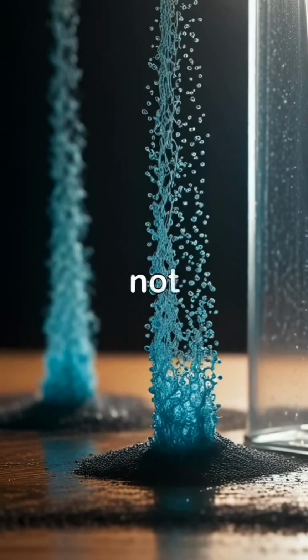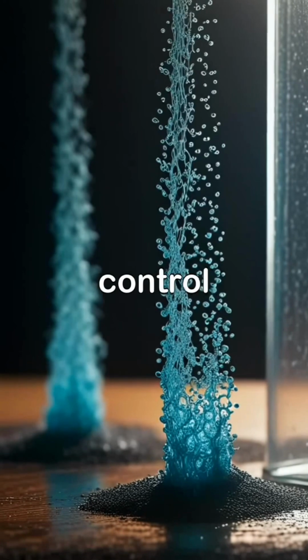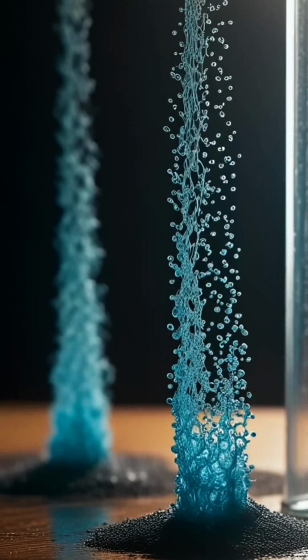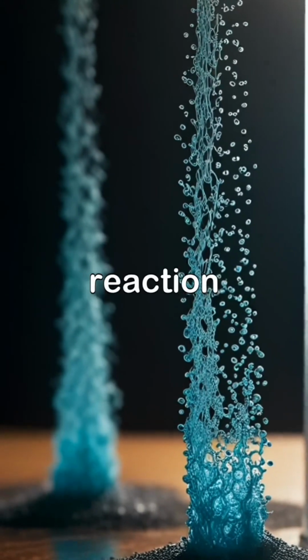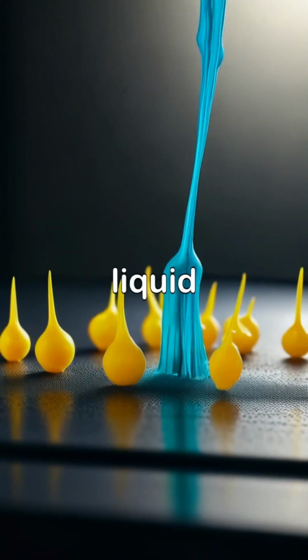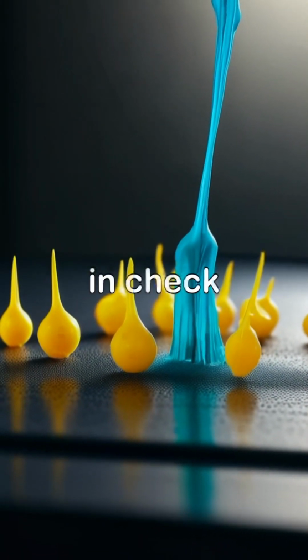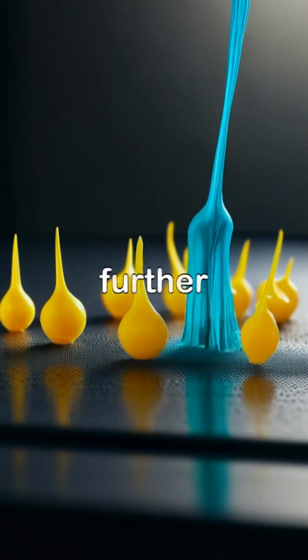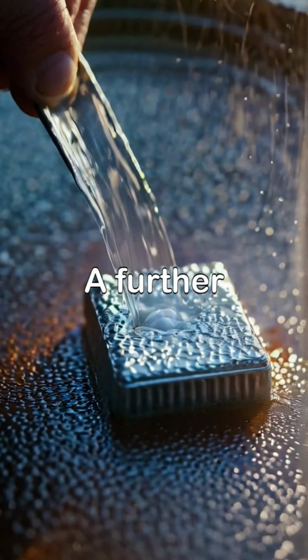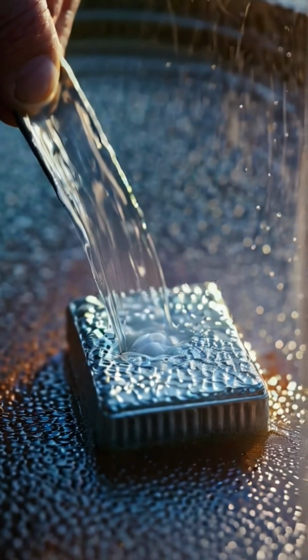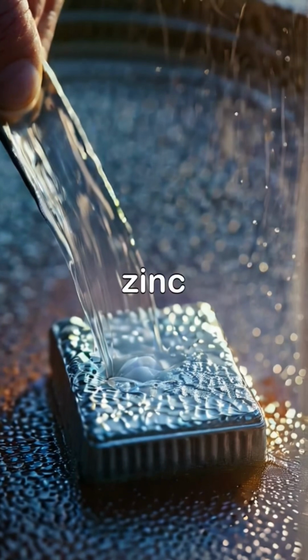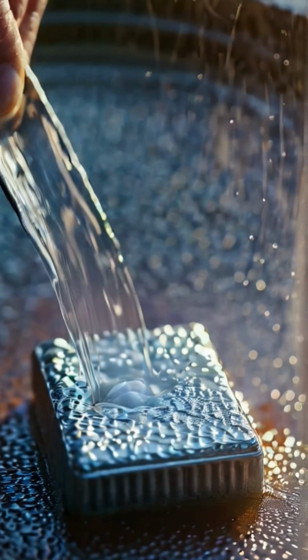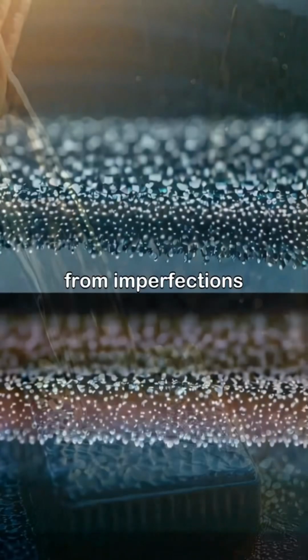We have so far not touched on those processes that control the rate at which reactions can occur. Consider, for instance, the powerful reaction between the oxygen in dry air and liquid aluminum. The reaction is held in check by the surface oxide film, slowing further oxidation. A further example is the beneficial effect of water vapor in strengthening the oxide skin on the zinc alloy during hot dip galvanizing, producing a smooth layer free from imperfections.